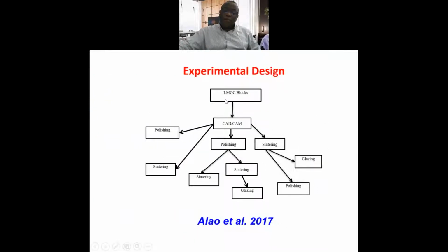You can see I started with lithium metasilicate glass ceramics, which is the one from the industry. Then these are the processes. Some of them are CAD/CAM milled. Some after the CAD/CAM milling underwent polishing, some sintering, some polishing and sintering, some polishing, sintering, glazing. Then some after the CAD/CAM milling, followed by sintering, glazing, some sintering, polishing. So we want to see which process can give the best or minimum surface roughness.